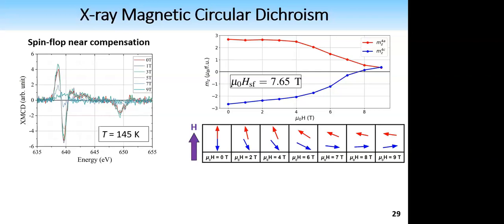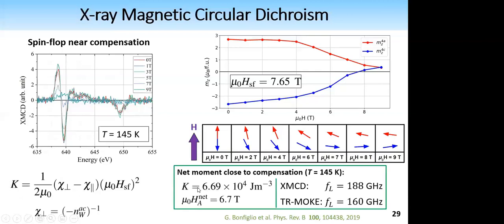We've determined the spin flop field to be 7.65 Tesla. Then, using the equation shown in the bottom left, I can obtain the anisotropy constant for the net moment. From the calculations, I find it to be 6.7 by 10 to the 4 joules per meter cubed, which is a typical value that we found again and again. Then I've also used the saturation magnetization to find the anisotropy field and used it to find the FMR frequency. What I find here is that for 145 Kelvin, we have 188 gigahertz. From TR-MOKE at similar temperatures, our colleagues found 160 gigahertz for similar samples. So we're in the right ballpark.